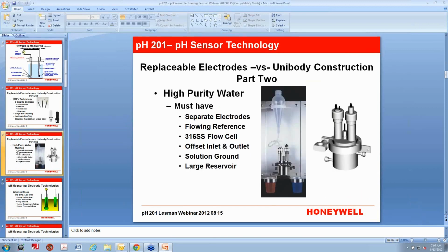Oh, sorry, part 2, I forgot. So part 2 is for high purity water pH. And actually, high purity water requires 3 separate electrodes because high purity water has to have a flowing reference, which means that we're using a liquid potassium chloride. And you have a reservoir that holds that potassium chloride with a tube going down into the reference electrode, and then the measuring electrode on the right.